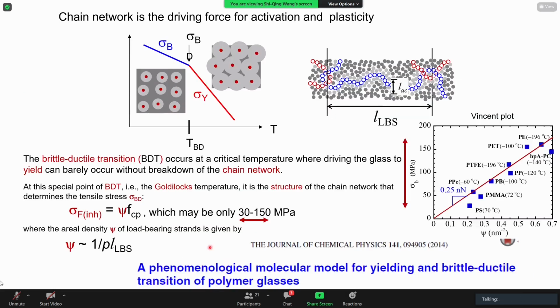So how should we model the theory of GC in both cases? I briefly indicate that in the case of plastics, we have worked out a model that describes how the inherent strengths could be related to the structure of the chain network. It turns out that much of the network can break down below the brittle-ductile transition through chain pull-out. So you could estimate the strength of your polymer, which is indeed a factor of 100 smaller than the theoretical limit, which doesn't occur, which is to say all the bonds bear load and all the bonds break. This is our old work, so I'm not going to show you more.